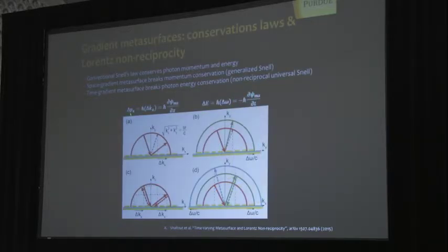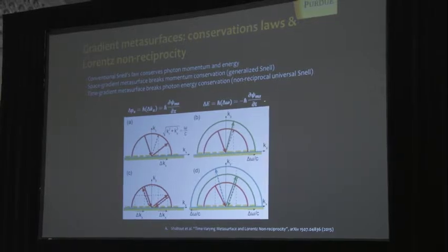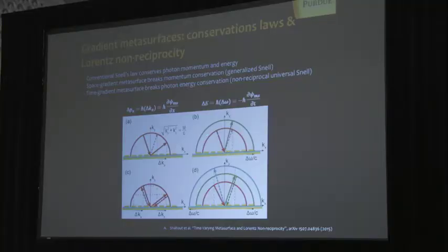So let me explain the ideas. This is conventional metasurface. This is isofrequency surface. When light goes to this interface, because of this additional momentum coming from metasurface, it doesn't go in this specular direction, but goes in this direction. However, if I send it back, it would go in the same direction. And now if I also modulate my phase in time, not only in space here, but also in time, modulation in time of phase means frequency shift. So it means that when it goes to this metasurface, it goes from this isofrequency surface to this one. And if I send it back, it experiences again shift in frequency and would go to yet another isofrequency surface, which means it would be non-reciprocal behavior.